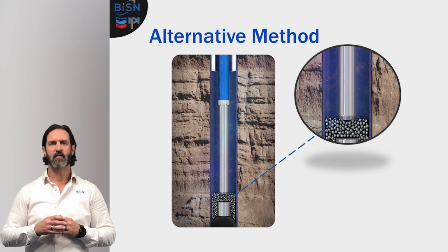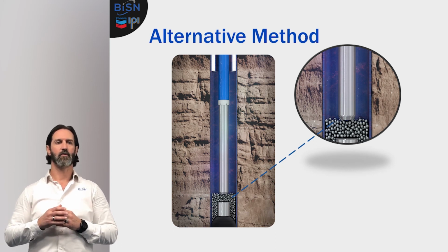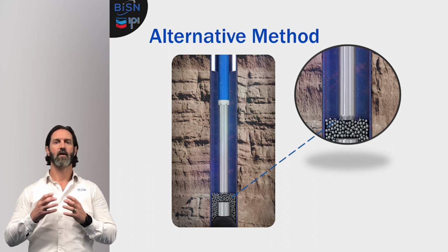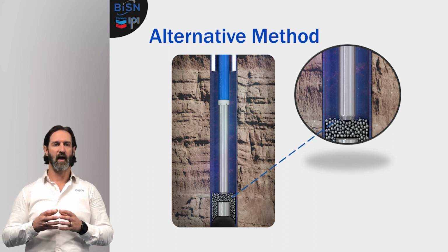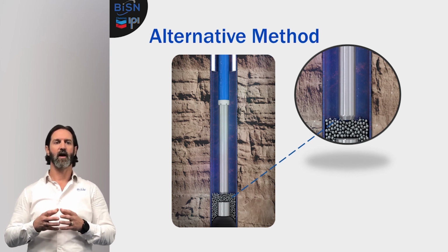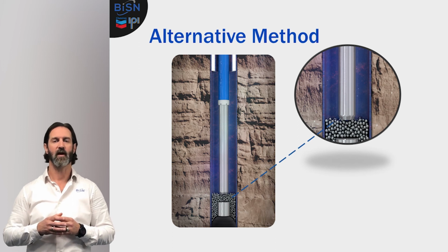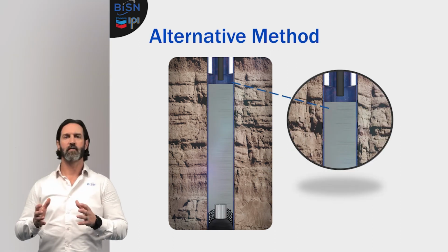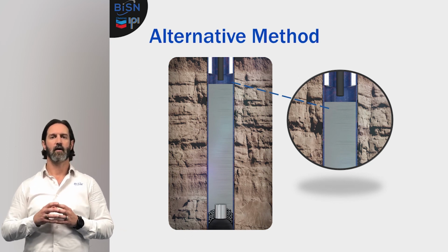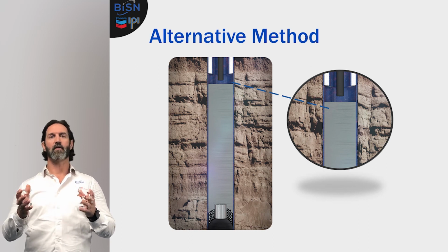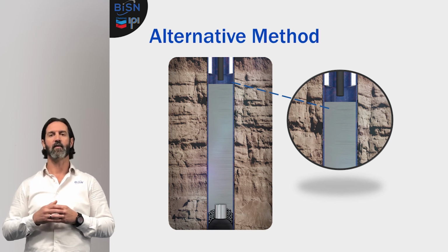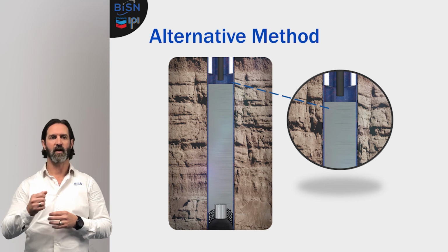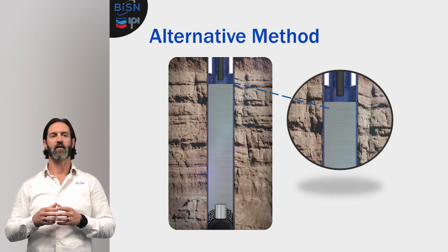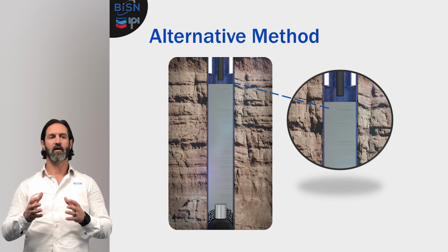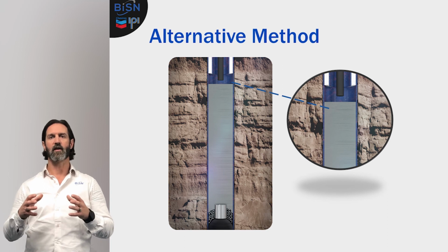With the bismuth alloy beads in place, on electric line, we run in with the tool. Again, this is the construction we talked about with the chemical reaction heater and the bismuth alloy cast on the outside of it. We just run down and set it directly on top of the bismuth alloy beads that we have put in place inside the section milled window area. Once the tool is in place, you activate the electric line. 240 volts, pulls about 60 milliamps, only need about 15 seconds of power. And then that will melt all the bismuth alloy just like you saw in the video. It will collect around the bottom of the heater. And in this case, as you can see here, we have extracted the heater. That's that black section that's being pulled up into the casing from the plug itself. And you're left with a solid alloy plug covering the section milled window.